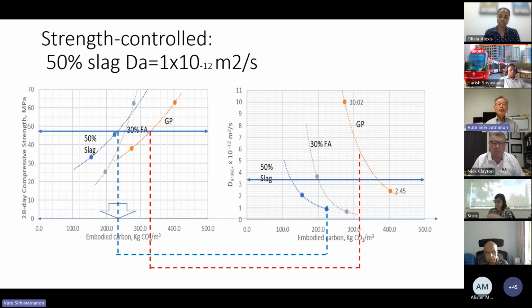At the end of the day, though, you need to choose the best concrete that meets all your performance requirements. And I'm merely showing you two performance requirements here, 28-day compressive strength and chloride diffusion. And that's basically the combination of the two data sets that I showed you earlier. So in this case, if you choose the 50% slag to produce a grade 40 concrete, basically it would demand about 230 kg of CO2, and that particular corresponding 50% slag mix will give you a diffusion value of around 1 times 10 to the minus 12 meters square per second, well below what is specified.